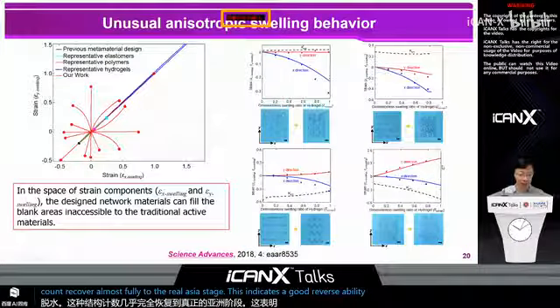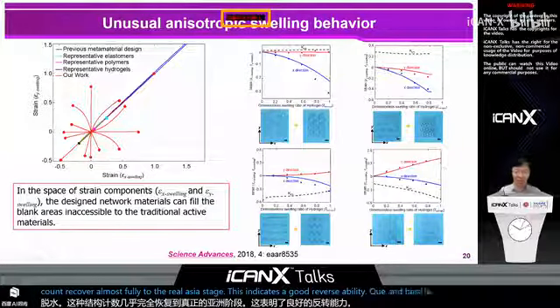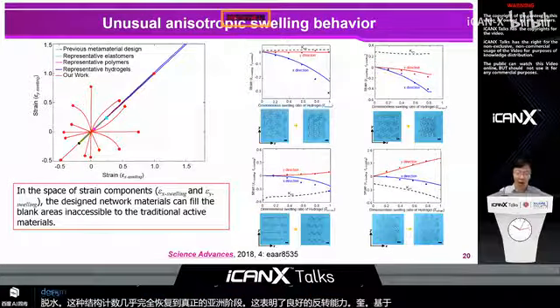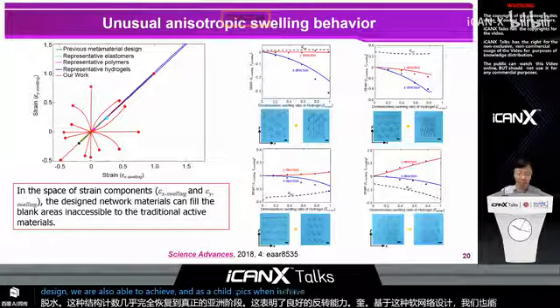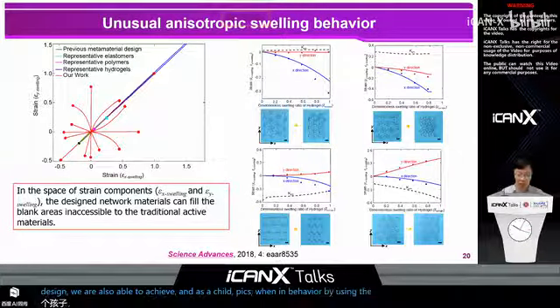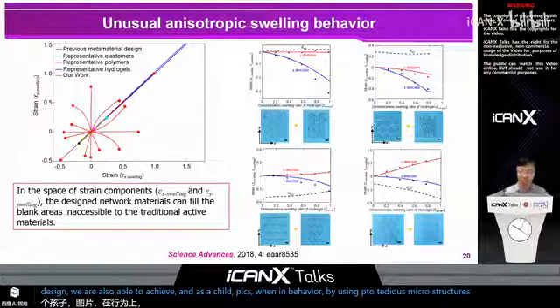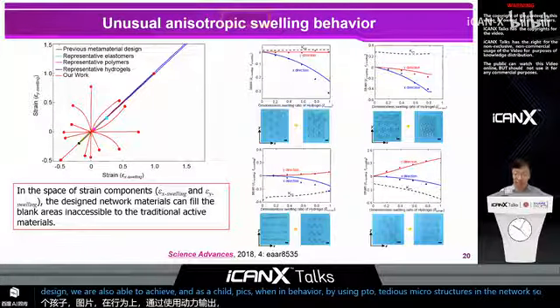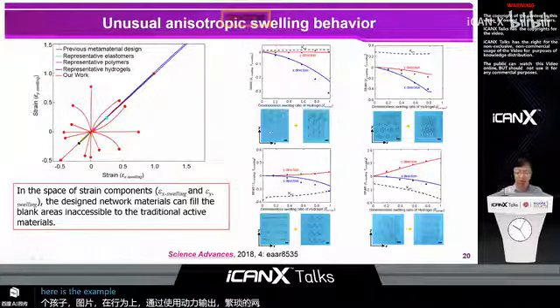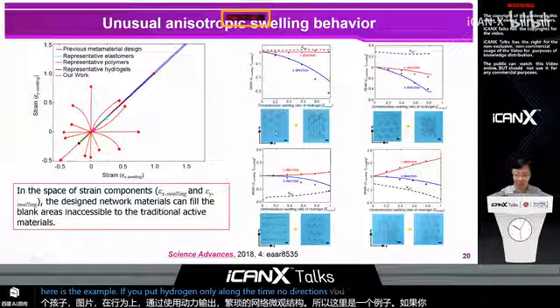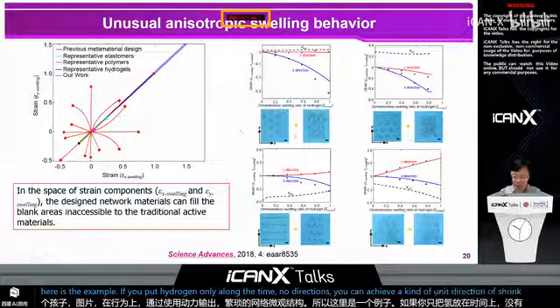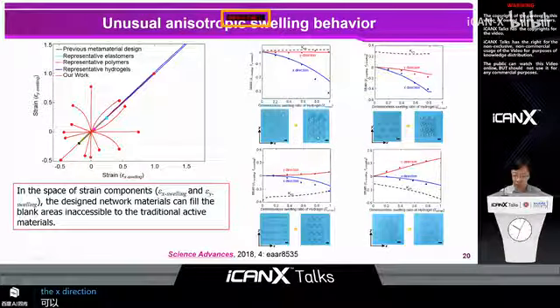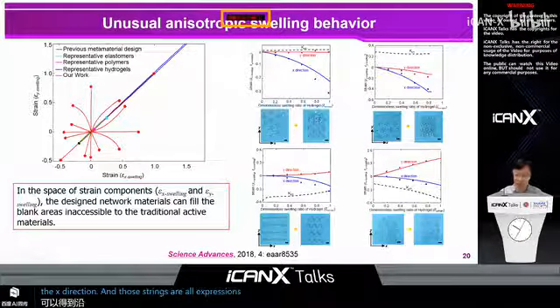Good. And based on this kind of soft network design, we are also able to achieve anisotropic swelling behavior by using heterogeneous microstructures in the network. So here is an example. If you put hydrogels only along the diagonal directions, you can achieve a kind of unidirectional shrinkage along the x direction and no shrinkage or expansion along the y direction.